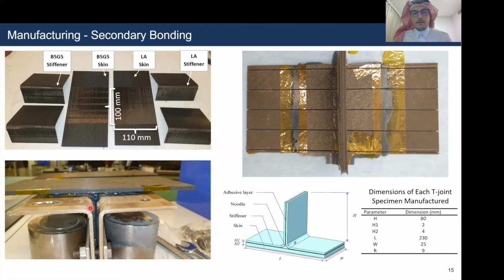Once the adhesive cured, the T-joints were cut using a water jet cutting machine and a diamond cutting machine. And the dimensions of each T-joint produced are shown here. It is worth highlighting that the length of the T-joint was 230 and the width was only 25 millimeters of each T-joint specimen.